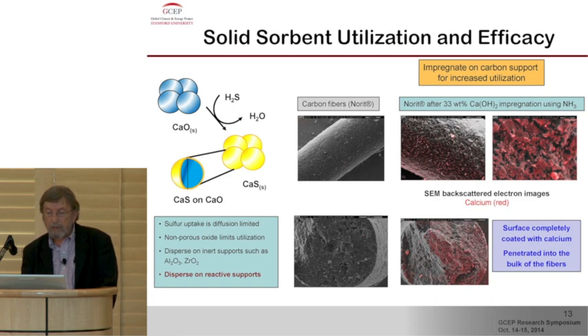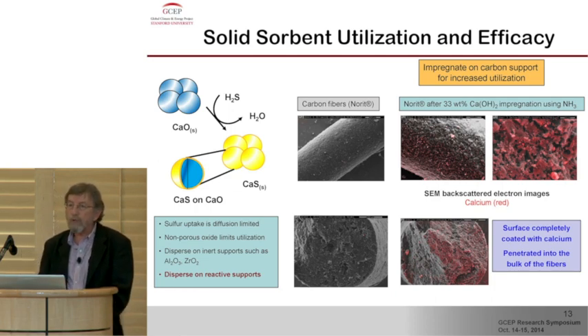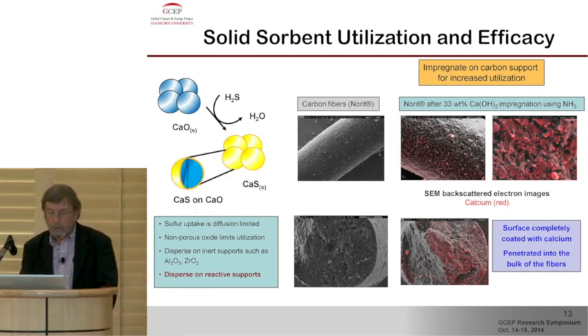Here is after impregnation of these fibers with calcium hydroxide, using ammonia as a dispersion. And you can see, on the surface, these red marks or red coloring are due to the calcium from the backscattered electron image. Both on the surface as well as within the bulk, we have a fair amount of penetration and impregnation of these into the materials.